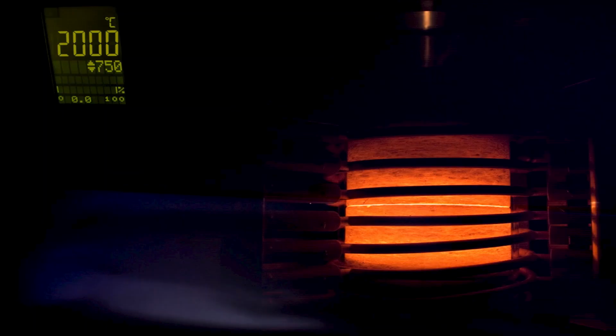So this is very bad from the silicon carbide point of view. And the good thing here, which we realized, was that there was a thin graphitic layer on the silicon carbide. So from a growth point of view, it was embarrassing to have this. But then one researcher from Chalmers said that I would like to have a look at this graphitic layer because I think it's quite interesting. So we intentionally tried to grow the thin graphitic layers. So we started the process, and we have a process where we explore this around a certain temperature.